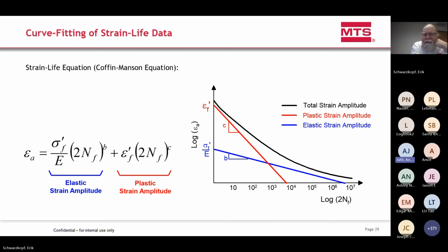Remember the Basquin equation from above. In this case, we're talking about a Coffin-Manson equation, which is a way to predict the strain life cycles, the strain amplitude versus the number of cycles to failure. The idea is that this can be divided into 2 parts. One part is based on the elastic strain in the cycle, and one part is based on the plastic strain in the cycle. And these 2 parts are shown in the blue and the red down below.